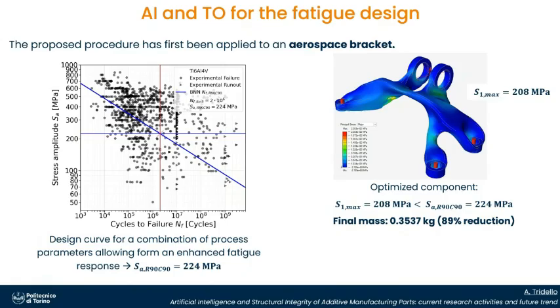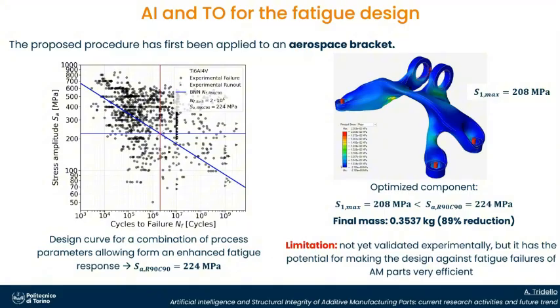This is the component which is optimized against fatigue loads, starting from the process parameter. So the first principal stress is kept below the limit stress. We have obtained a final mass which is well below the initial mass, and this is very good. But the most important thing is that if we want to produce these components and we have a set of process parameters, we can take them into account directly before the optimization process. The limitation is that we have not yet validated it experimentally, okay? But it has the potential for making the design against fatigue failure of additive manufacturing parts very efficient, which is something quite new and not considered in the literature.